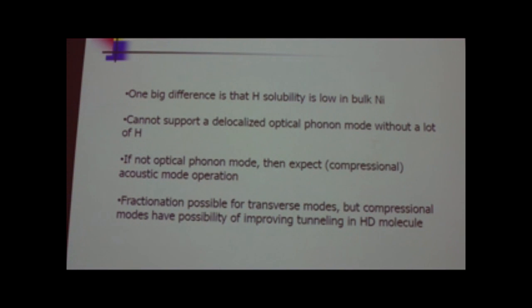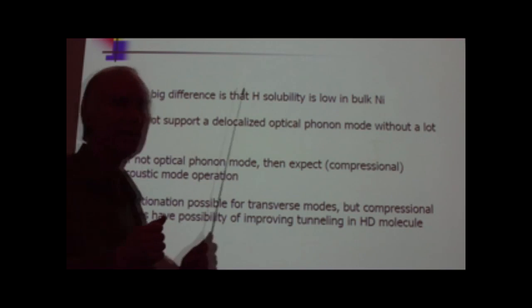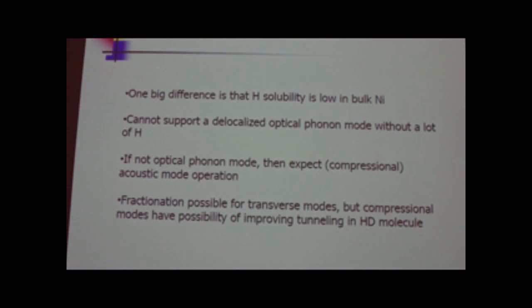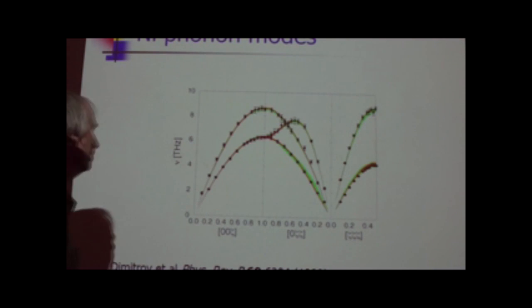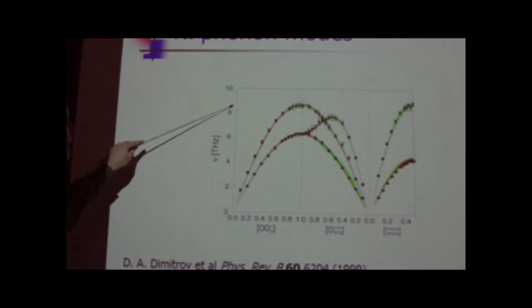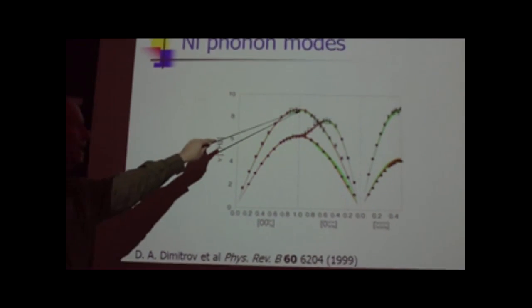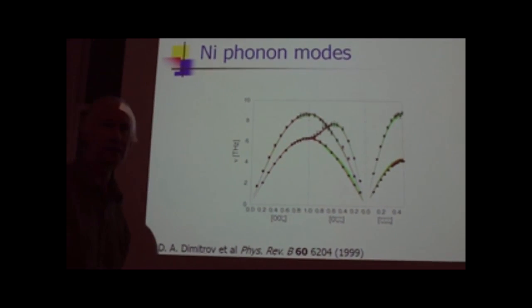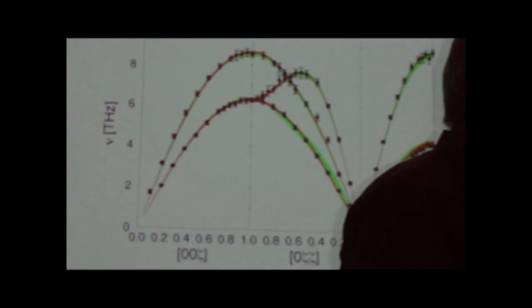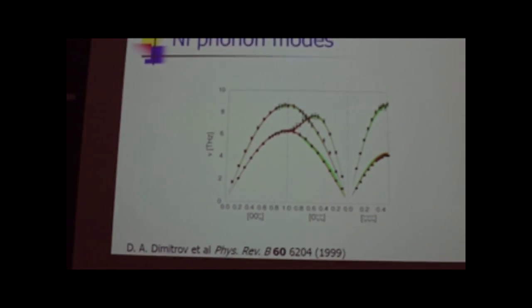Fractionation seems possible for transverse modes, but the compressional modes, as we argued before, would have an advantage of being able to bring the atoms of the molecule a little bit closer together and make a change in the tunneling. So here's what the phonon modes look like for nickel. Basically, they're higher frequency than in palladium, so you can go up to high 8 terahertz at the top of the acoustical phonon band, which in my view would be the preferential place for the system to work.